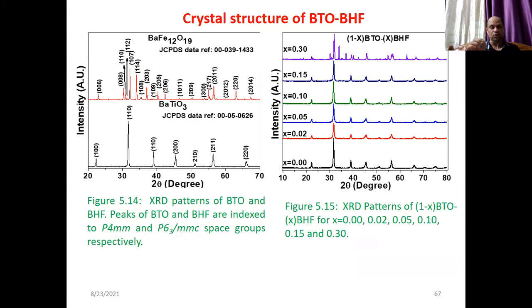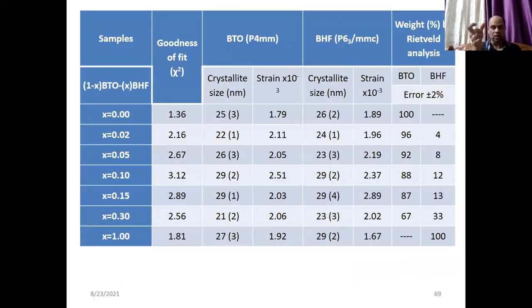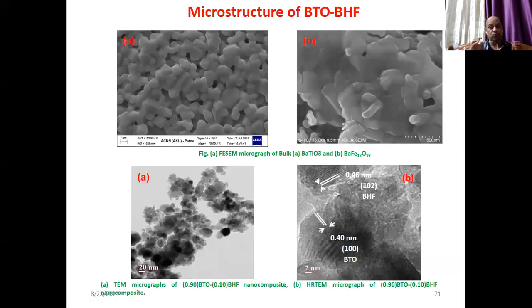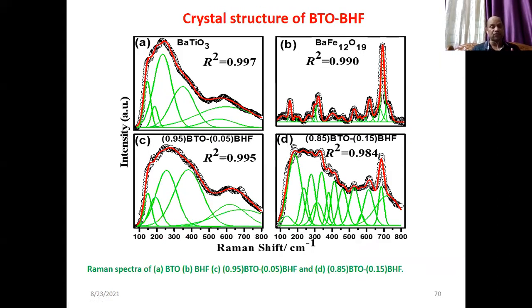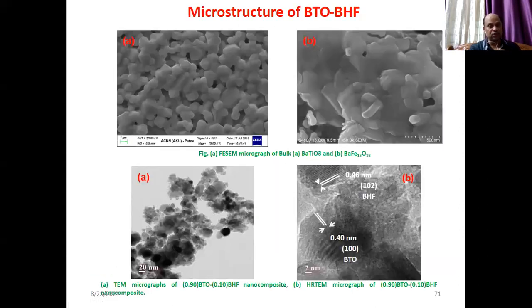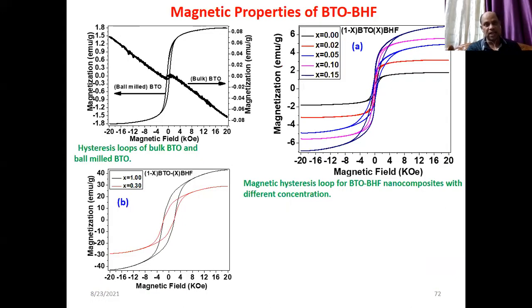So this is the BTO BHF, and in the same way we prove that they exist together. We also find out the percentage of its crystal symmetries. Then we go on to check whether there is any reaction. So Raman tells that there is no reaction at the interface. You cannot say 100%, and within the experimental error there may be a little reaction, but in the major way there is no reaction. Again, TEM tells that they are sitting together.